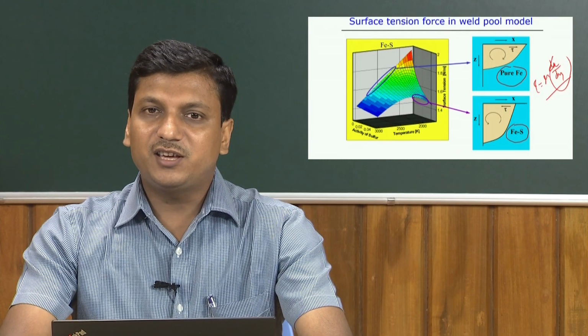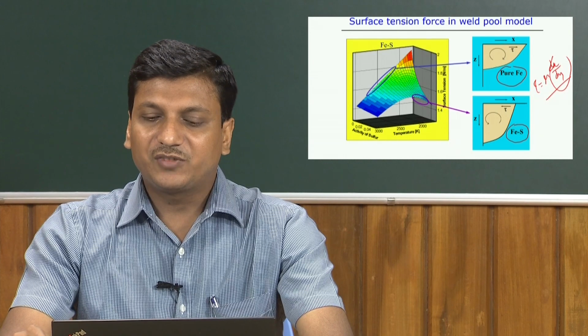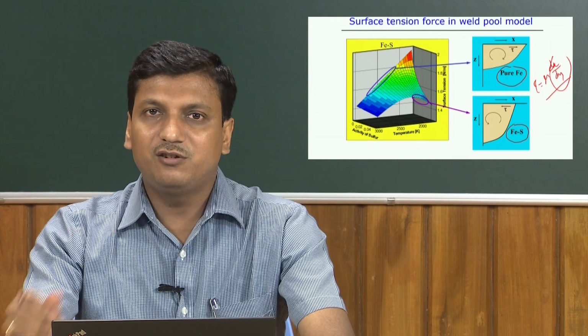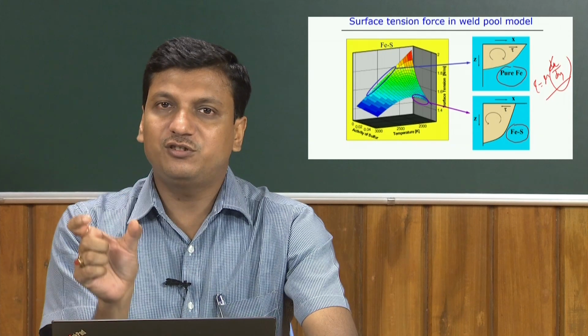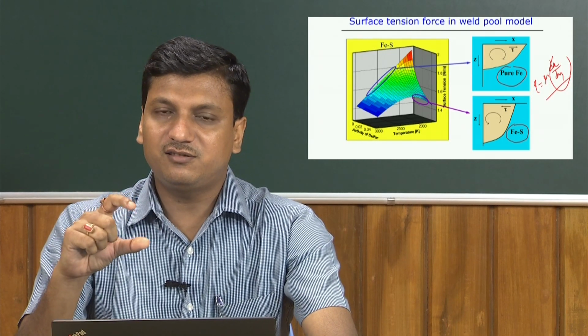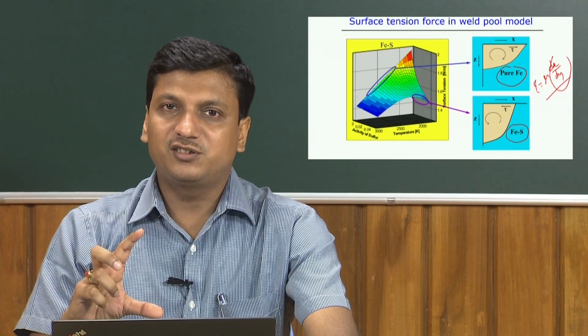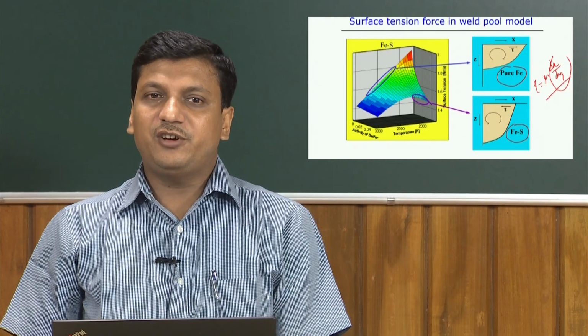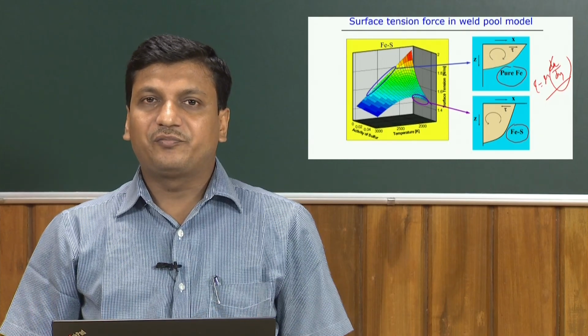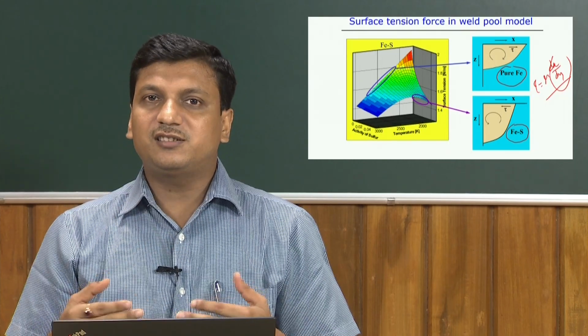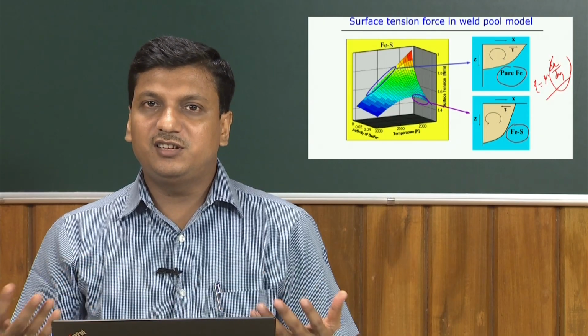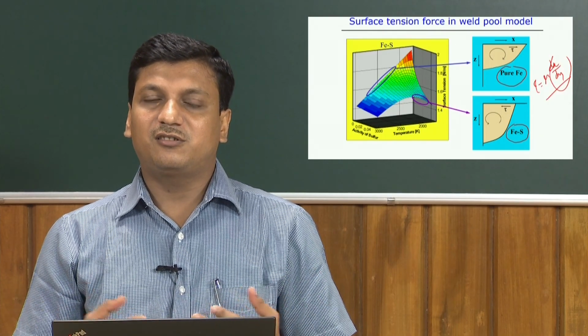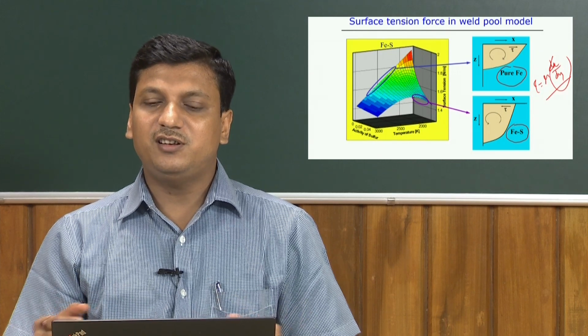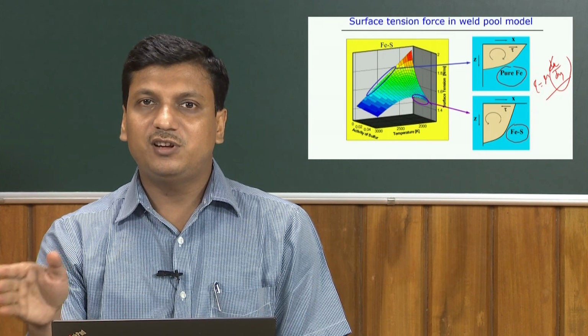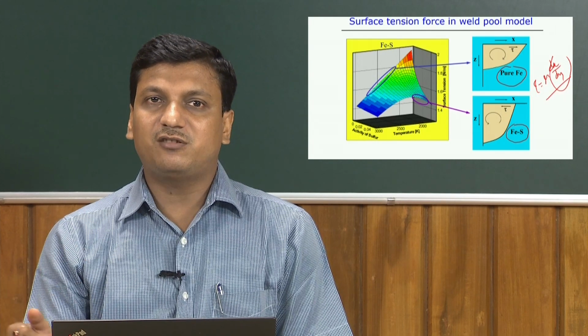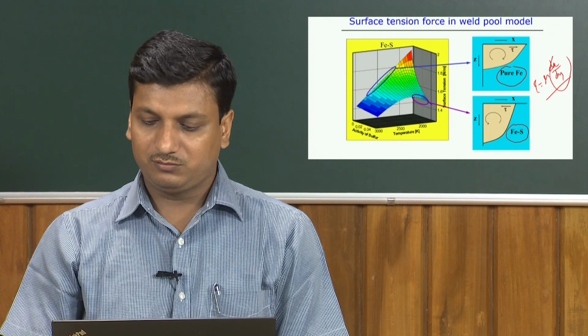So, when it is making the clockwise metal flow, that impacts the final weld pool shape. It actually decreases the weld width, but it tries to increase the depth of penetration. In this way, once the surface tension force gradient changes with respect to temperature and the concentration of the surface active elements, it finally influences the Marangoni convection of the weld pool and impacts the shape of the weld pool.